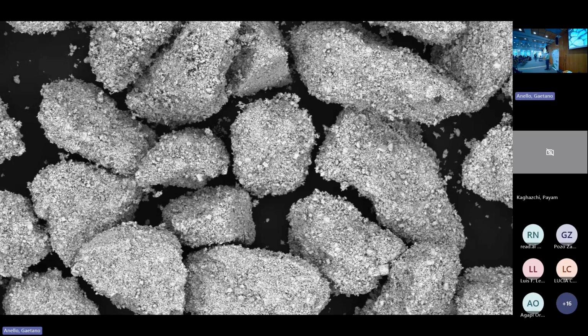possible. But the problem is that for CO2 to methanol, you need a high pressure, reductive atmosphere and, let's say, low temperature, 250. But for MTO, methanol to olefins, you should operate at atmospheric pressure, no reductive atmosphere, but high temperature. And with a tandem catalyst, we can try to bridge them together.